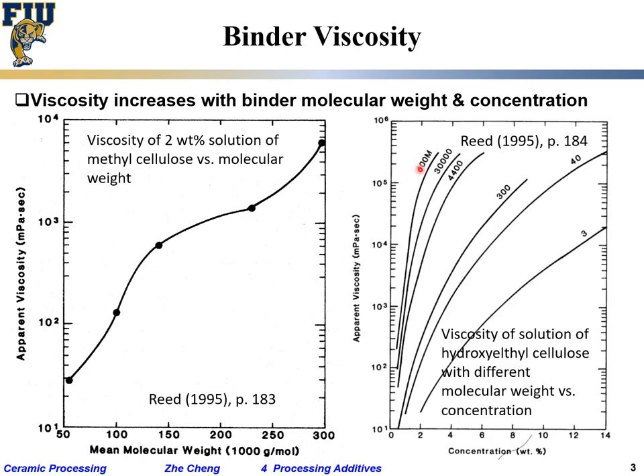For the same molecular weight of methyl hydroxyethyl cellulose, by increasing the concentration, the viscosity increase is also dramatic. So you have two knobs: changing molecular weight and changing concentration. However, you cannot add too high a concentration because if you have too much binder, as you dry the material it will contain a lot of polymer, and when you burn it out you get a lot of porosity, which is catastrophic for densification or sintering.